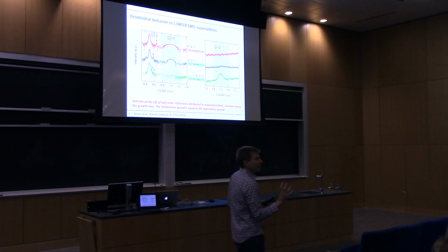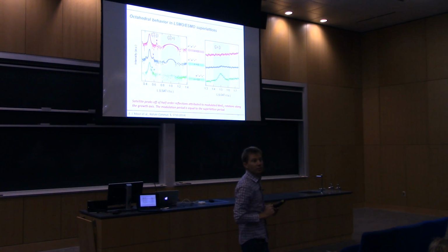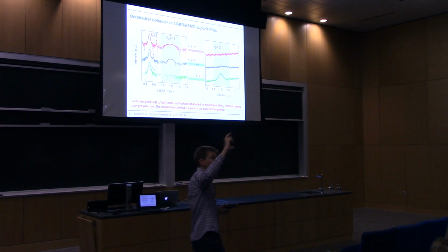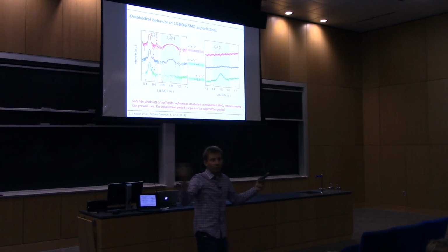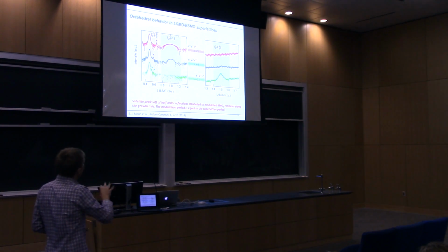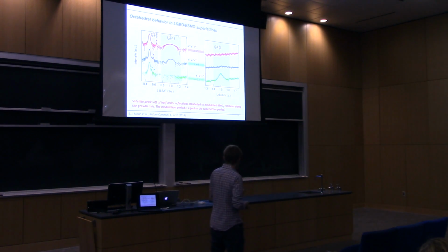So that tells us that we have a modulation of this unit cell doubling distortion, which are the octahedral rotations, right? And the periodicity that we get from this satellite peak matches the periodicity of the superlattice. Okay? So the octahedral rotations are modulating about the C-axis with the period exactly what we would expect of the superlattice. There's a bit more information in here that I can talk about if someone's interested, but that's the main takeaway. We have this modulation.